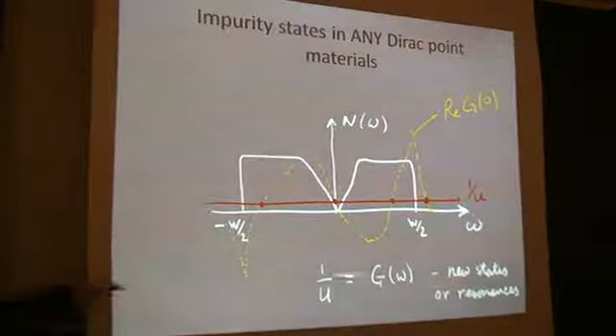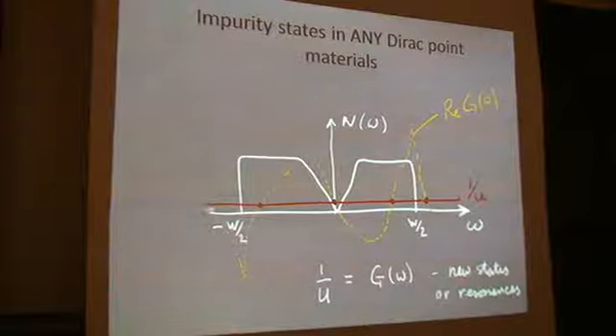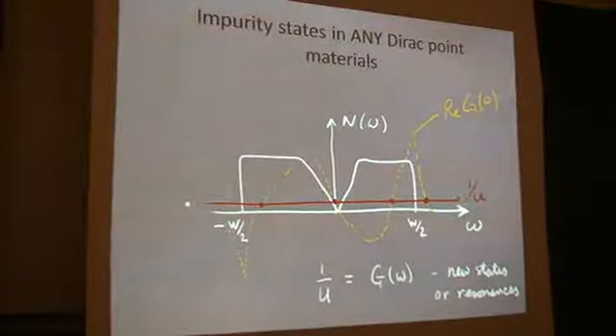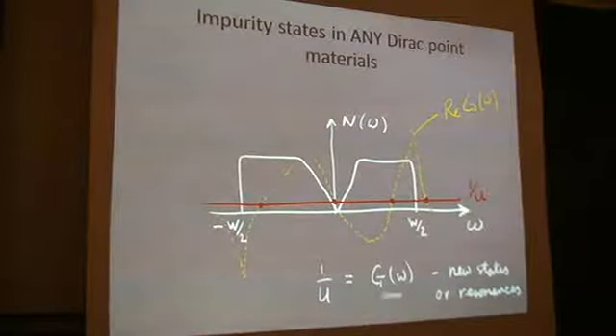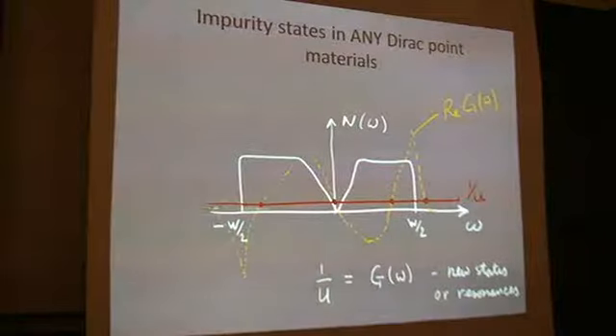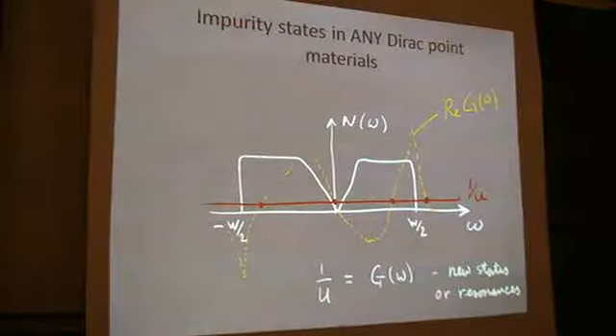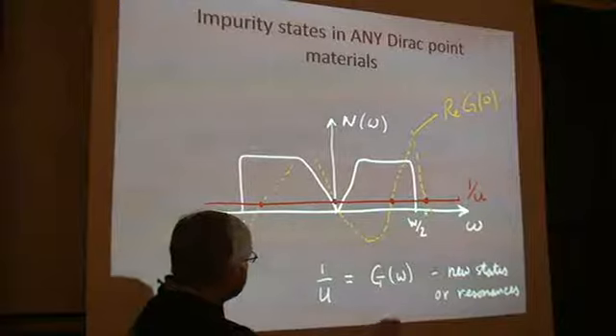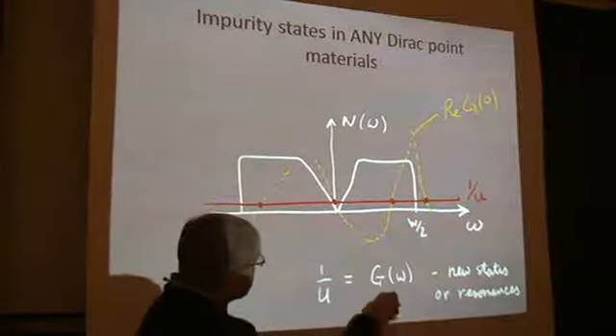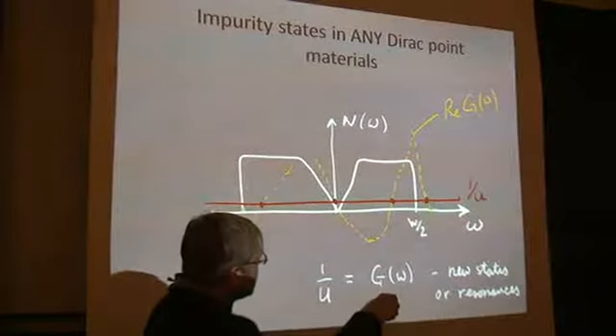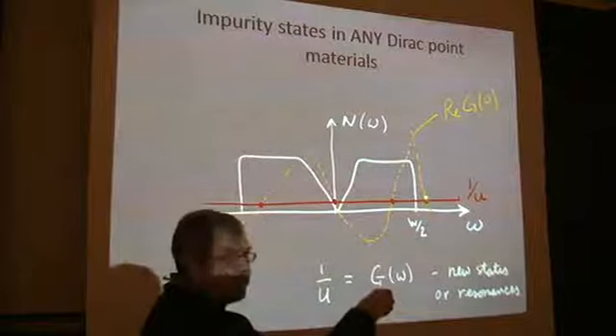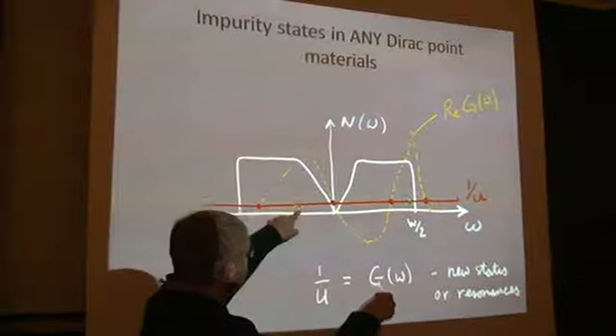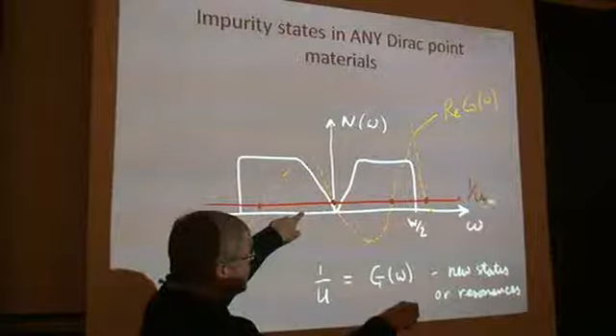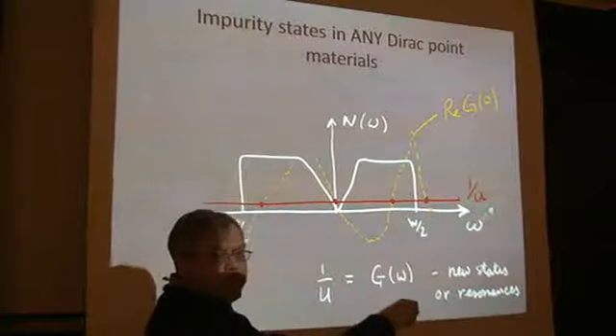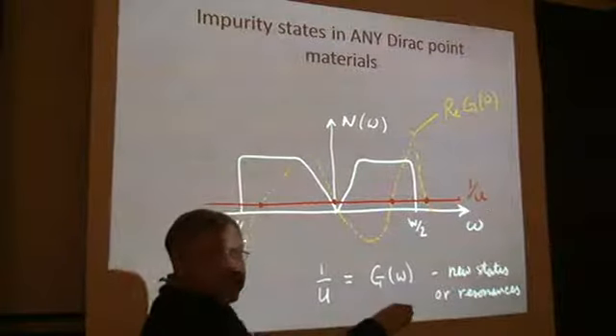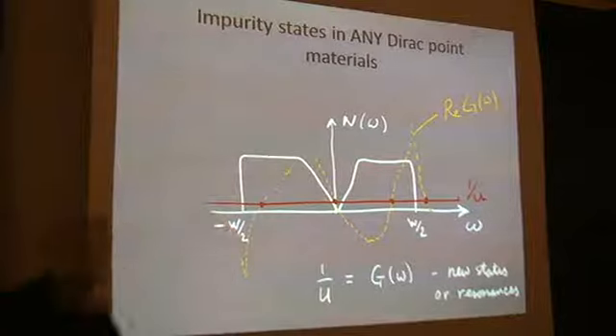Now, I'm coming in with a very large U, so I'm drawing a very low line, horizontal line, and I'm seeking where both real and imaginary part conspire to satisfy that this horizontal line intersects them at the same time. Now, number one state you can see right away is actually for very large U, I have an anti-bound state. This is like an upper Hubbard band state. If this state is pushed outside of the continuum, and the larger the U is, i.e. the lower the line, the more and more toward the right my anti-bound state will move. So this one behaves as our conventional intuition would predict.